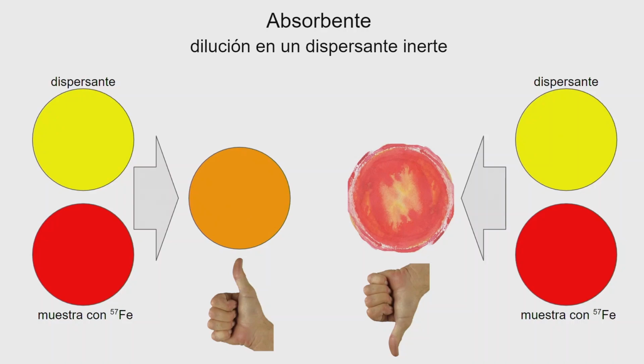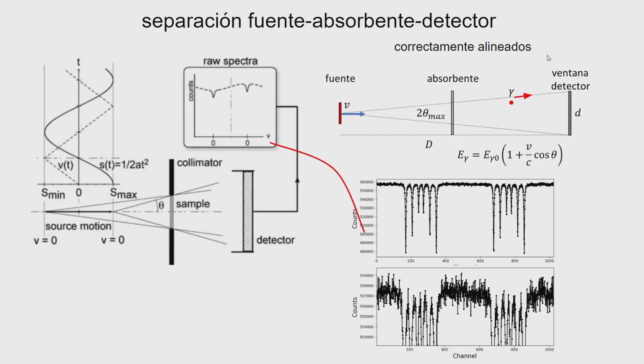Well, sometimes you need to make a dispersion. You have very little absorber, or for some reason you need to disperse the absorber in an inert substance, which must be inert in the sense that it doesn't interact with your sample, chemically for instance, or magnetically, or whatever. But also, from the point of view of having very low absorption of radiation, it must be done with a species of atomic number as low as possible. And then you make a dispersion of your sample into this material. And again, you need to have a very good, very homogeneous dispersion. Not something like this, but rather something like this.